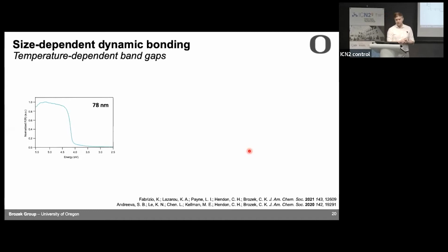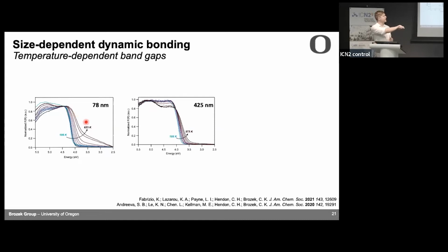And we said, all right, let's study their optical absorption as a function of size. But we wanted to do this without any guest molecules, so no solvent, nothing in the pores. We wanted to look at the intrinsic optical properties of the MOF. So we took a UV-vis spectrum of about 80 nanometer particles, and at the same time, we evacuated and heated the nanocrystals because we wanted to activate them. But when we did this, we saw something really unexpected: the optical absorption was strongly temperature dependent. Well, that was weird. So we asked, is this true for all sizes? When we repeat this on larger particles, we still see a temperature dependence, but it's not nearly as severe.